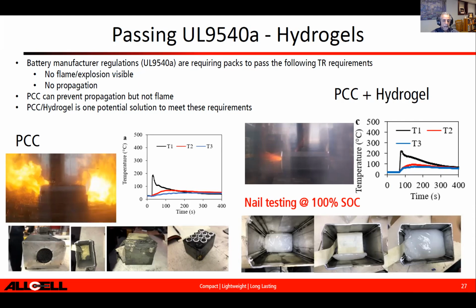Once you do the PCC or the phase change composite to stop propagation, the other issue, how to handle the flame, and what we developed is a combination of manifolding and also a hydrogel material that can actually help with that flame extinguishing inside the module. Hydrogel are super absorbent polymer. They're very common use in baby diapers. What they do is they can absorb water probably 10 or hundreds of times their weight.